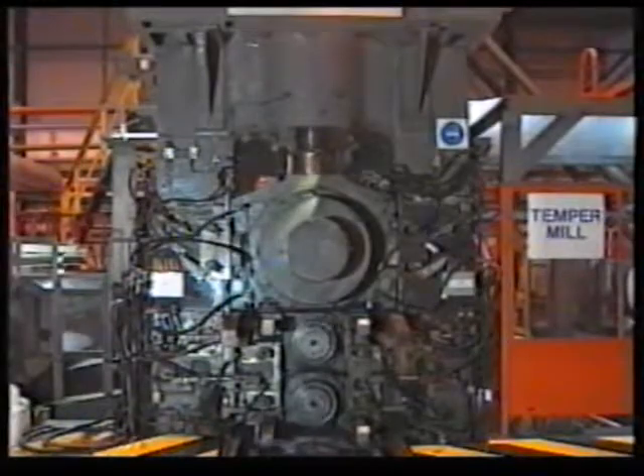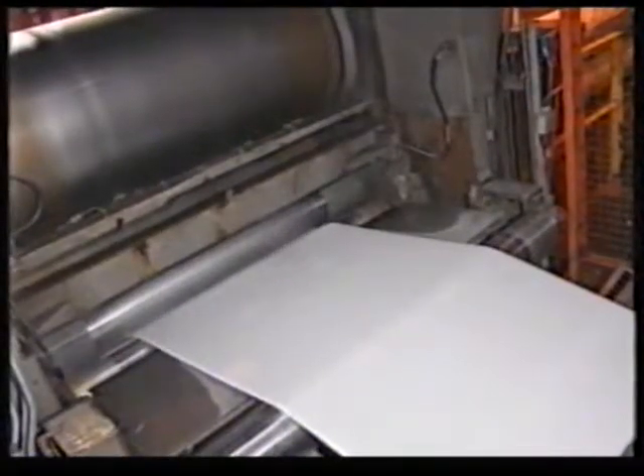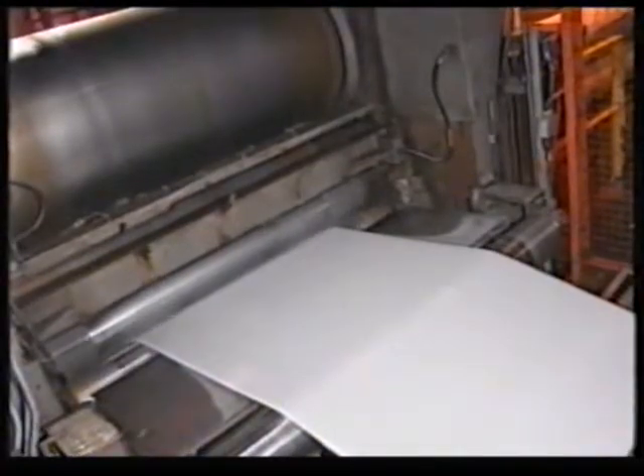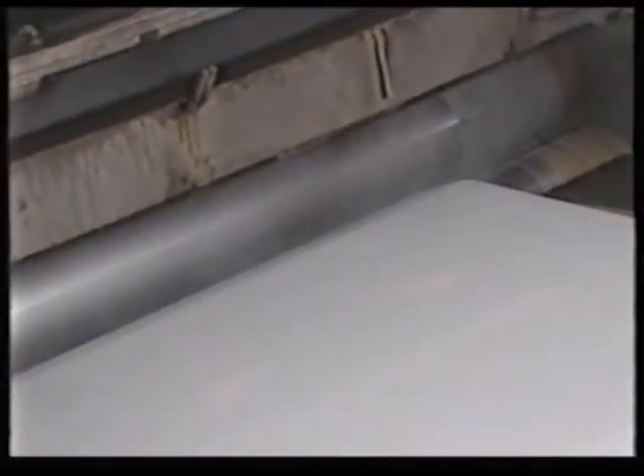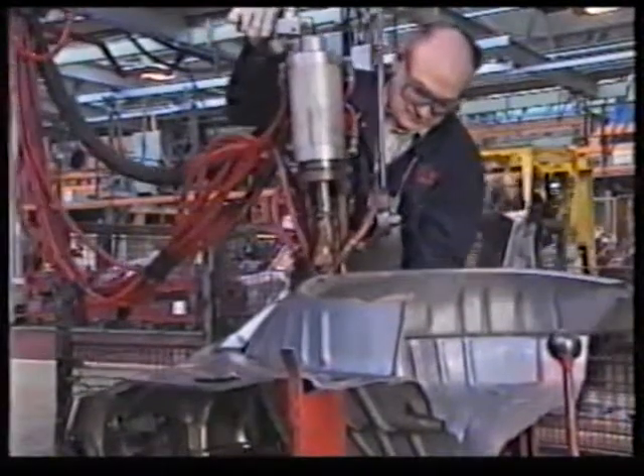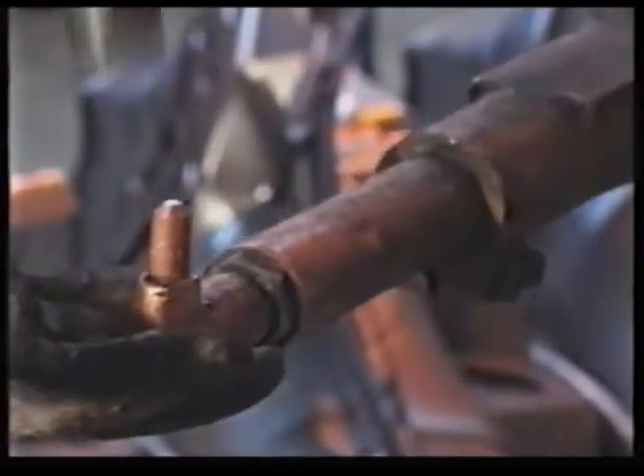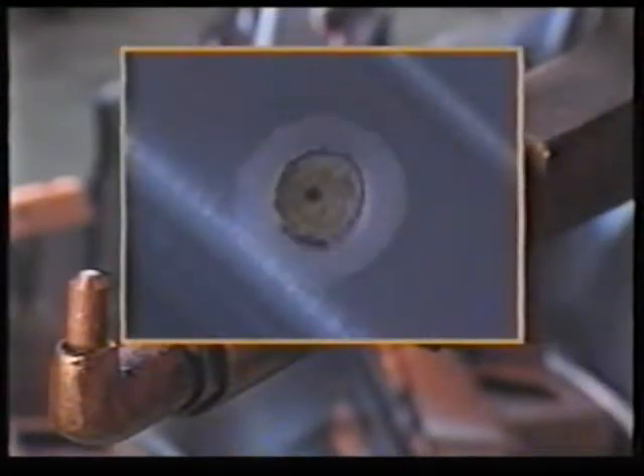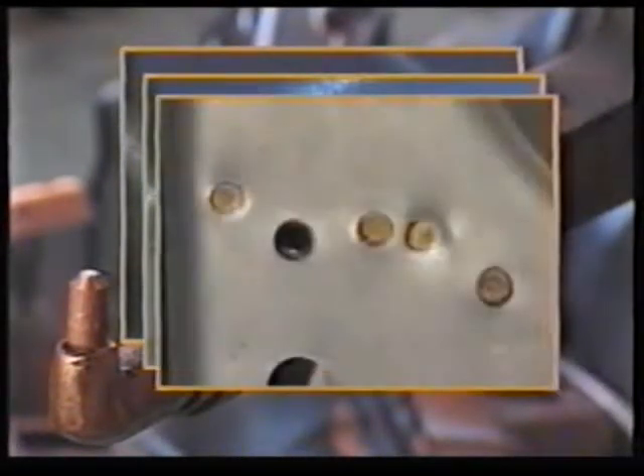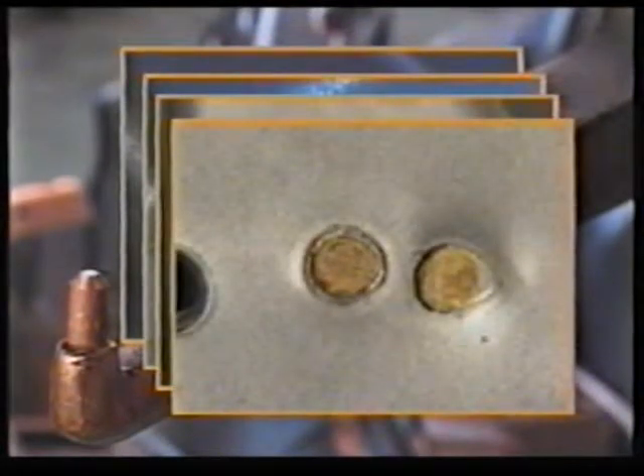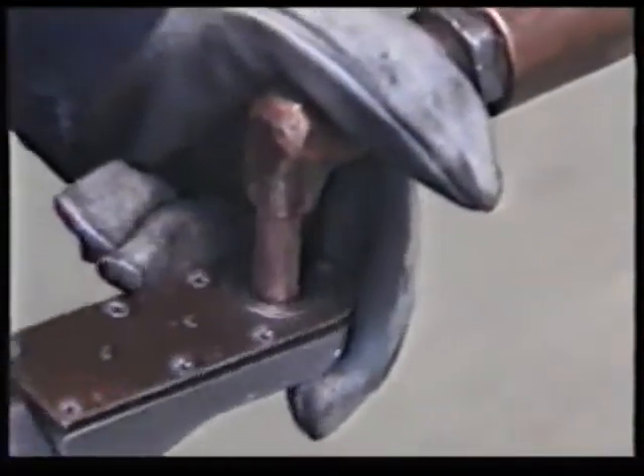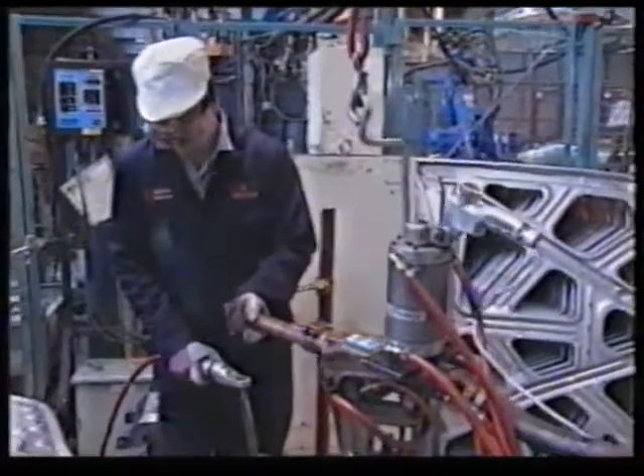In the tempering process which follows, fissures develop in the surface, and these help the paint key into the coating. Also, within the alloy, a hard phase develops. And this means that less zinc is melted out of the surface layer when it's spot welded. Molten zinc reacts with copper in the electrode, forming brass, which you can see in these spot welds quite easily. It also affects the electrodes, which have to be redressed frequently to maintain the correct current density at the tip.